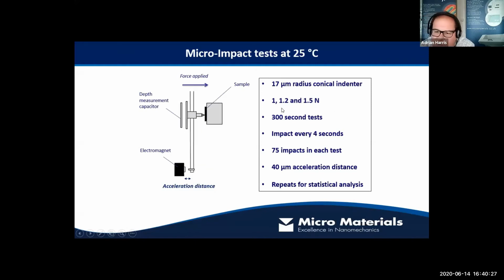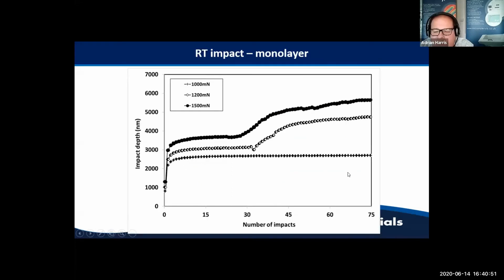We used various impact loads of 1, 1.2, and 1.5 newtons. One impact every 4 seconds for a 300-second period, so this is a 75 impact test. We're accelerating the probe from 40 microns away from the surface, and we've done several repeats of each test on each sample to get some statistical certainty. So this is what impact data looks like.